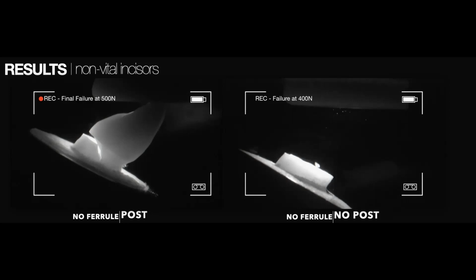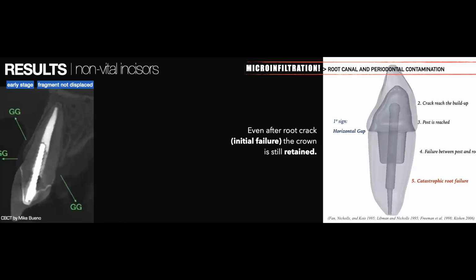But when you have a no post approach, most of those failures, when they happen, go either for restoration fracture without breaking the tooth, or it breaks a piece of the tooth because it's so well bonded, right? It removes a piece of the root, without going under the bone. We call that possibly repairable, because I didn't lose the root. I can still redo the restoration, okay? So what's the clinical implication of those initial failures?